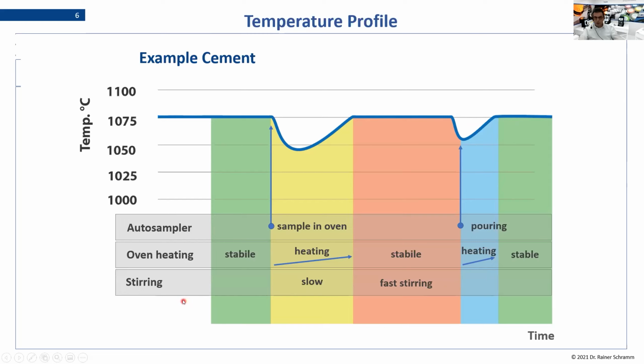If we look at the agitation, then there we have introduced something new. Because we have a round furnace, we rotate our samples all the time. That means after introducing them into the furnace, we rotate the bottom like you know it from the microwave. And in this way, we homogenize the temperature distribution in the furnace, so that like your food in the microwave, also the samples here, every sample sees the same heat. So this guarantees an extremely high precision. And then once it's liquid, we do a fast agitation, really to homogenize it inside the crucibles.